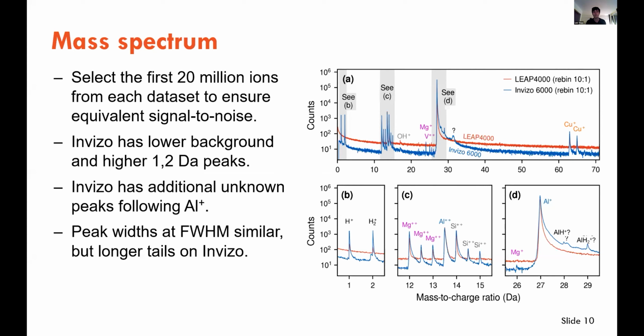Peak widths, the full width half maximum, I found to be relatively similar, but with longer tails, longer thermal tails, that is. But with a lower background, this may end up leading to greater chemical sensitivity. This alloy isn't really the best for studying that, though. Its composition is rich. Nothing is particularly dilute in this alloy.